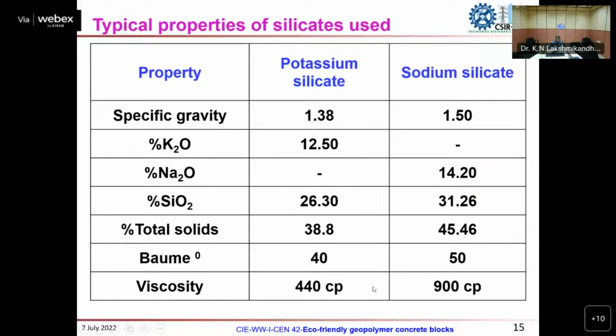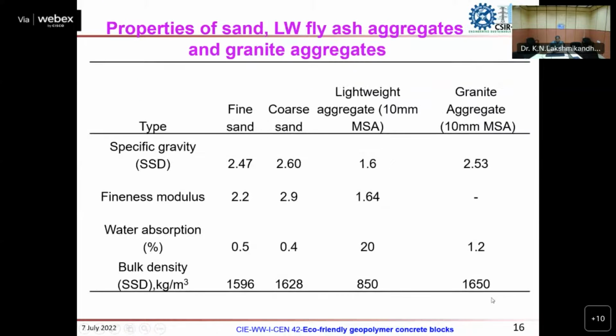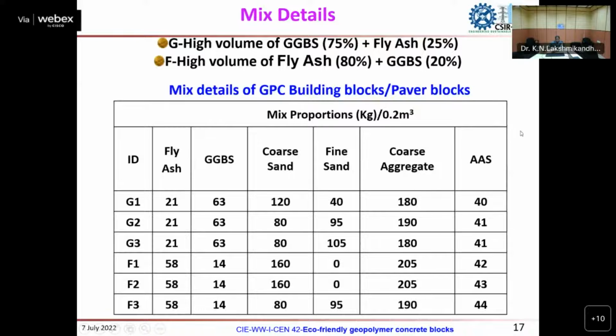And again, the viscosity, when you are preparing hydroxide solutions of about 10 molar, affects the workability. There are some issues, but potassium based systems seem to be more workable. And at factory scale, we have used fine sand, coarse sand, as well as some hollow bricks, and lightweight aggregate, fly ash based lightweight aggregate also. Some blocks have been produced other than the normal solid blocks: paver blocks and building blocks.